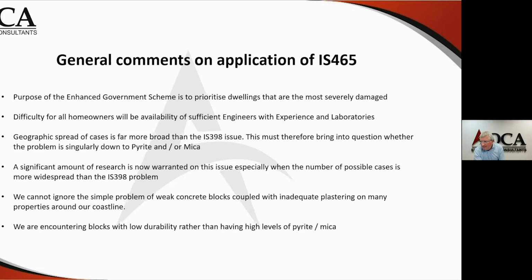So these are all exposed west of Ireland counties. If you're building a house close to the coast in these areas, which have a designation of high exposure, you must be using 3 layers of plaster. But that is rarely found on the west coast of Ireland. And therefore, if we're not doing the plaster in an appropriate way, are we then saying that our concrete blocks